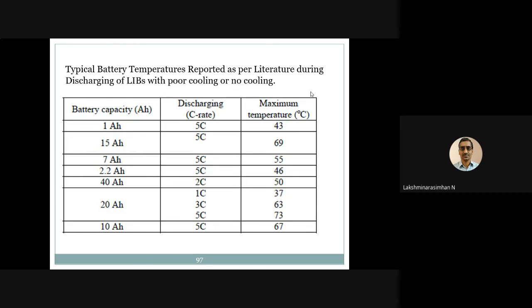So this 50 amperes will be drawn in this case, in the 10 ampere hour battery. Just drawing 50 amperes is big. And you see the temperature is only 67 degrees centigrade. So that's how the cooling is there. But if you have very good cooling, you can even bring down the temperature to 50 degrees or even less than 40 degrees. That's very important.